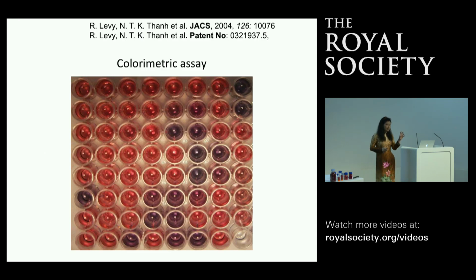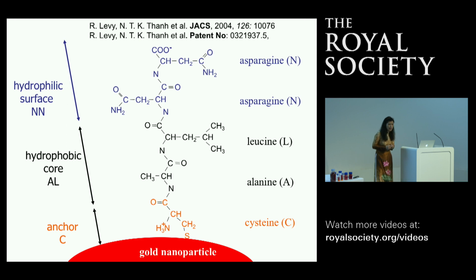Then you can see that the color of the gold nanoparticles changed from red to purple. So you can use it as a very simple assay, and again, I just said about 600 citations, and actually for this work, we got a lot of citations as well. Because it's just a simple color assay you can do, with UV-vis spectrum scans, and you can see whether they aggregate or not. And later on, we looked into the stabilization of gold nanoparticles using peptides. A peptide is a building block of the protein.